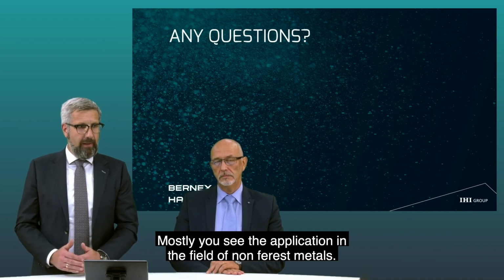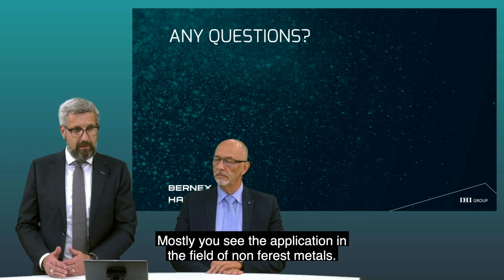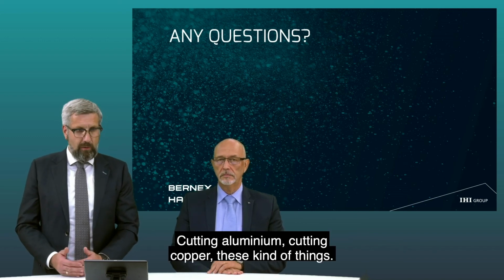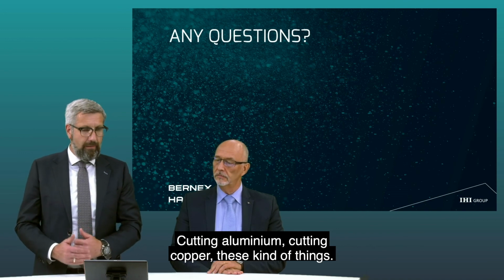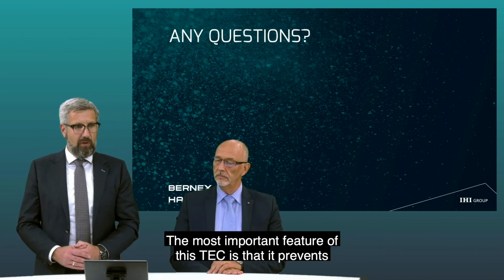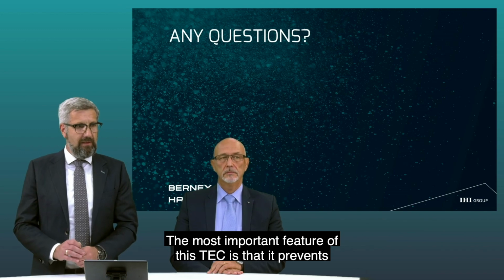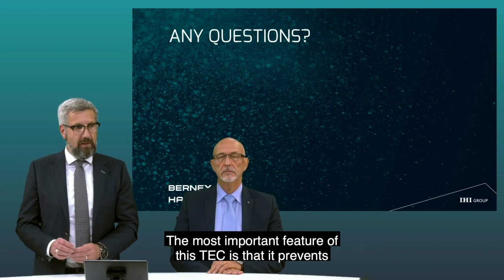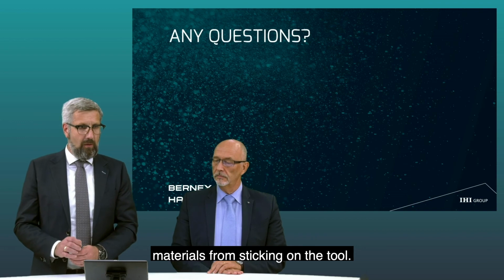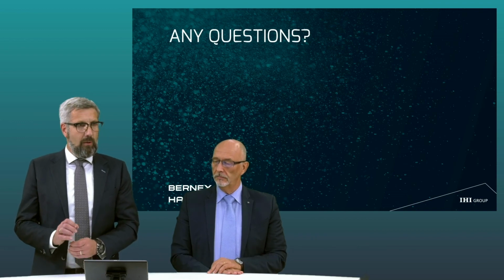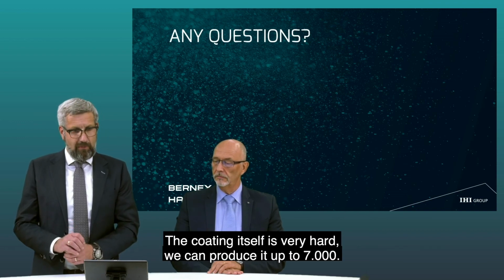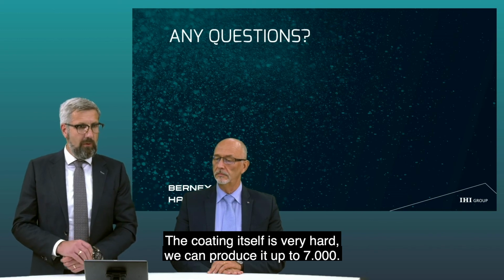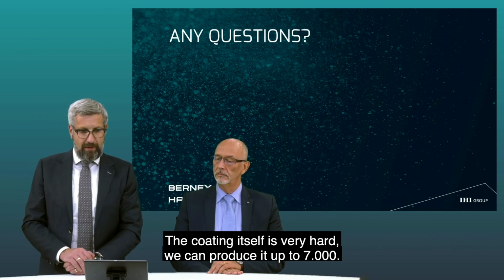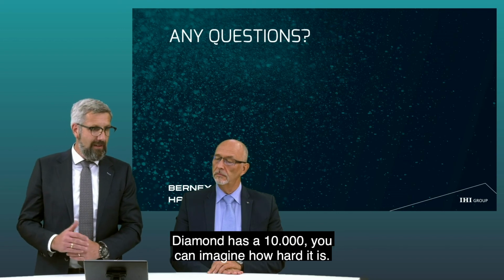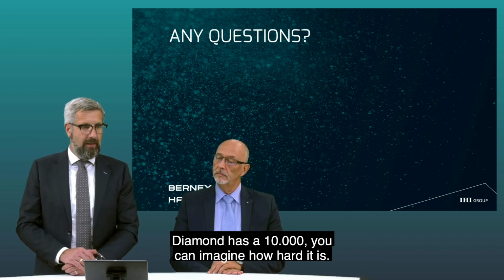So the application is mostly in the field of non-ferrous metals. So cutting aluminum, cutting copper, this kind of thing. The most important feature of this TEC is that it prevents material from sticking on the tool. The coating itself is very hard. We can produce it up to, let's say, 7,000 Vickers. And if you know diamond is 10,000 Vickers, you can imagine how hard it is.